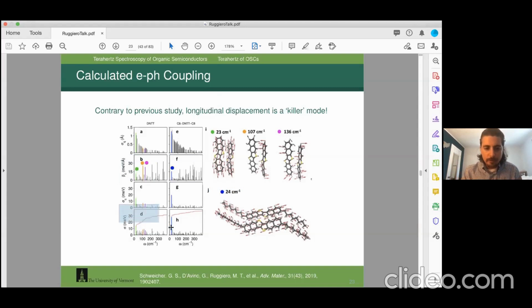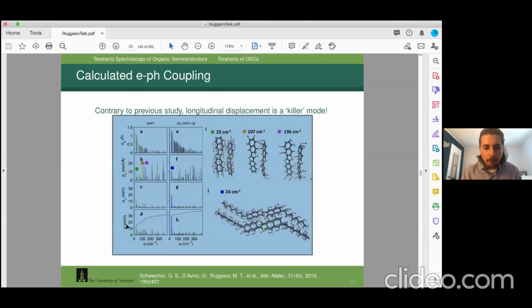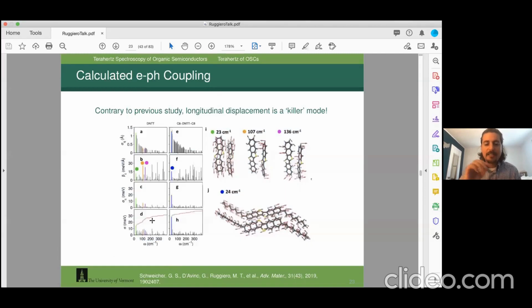And then the ultimate result, on the bottom here, is the product of these first 2 panels, essentially. Because if the motion is lower in frequency, it's going to move more, and so it's going to have more electron phonon coupling the more motion there is. That leads us to this bottom panel, where the red line is the integral—the total electron phonon coupling of all the modes—but each bar is the individual modes, showing how much they contribute.